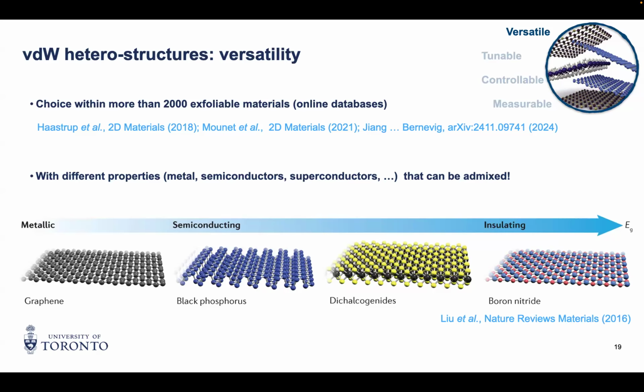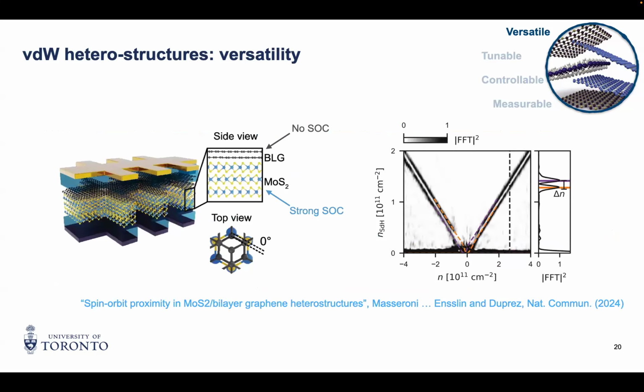Just one example of something you can do is put graphene on top of a material that has a strong intrinsic spin-orbit coupling. Graphene was envisioned for a long time as the next generation transistor, but it's always hard because there's no gap. So there's always some leakage current, and you would like to open a gap. One way to do that is to add some spin-orbit coupling onto graphene. Just by proximity effect, you can deposit graphene on top of MoS2. This is a material with spin-orbit coupling, with big atoms like molybdenum. And that's enough to open the gap, which was measured here in graphene through Shubnikov-de Haas oscillations.